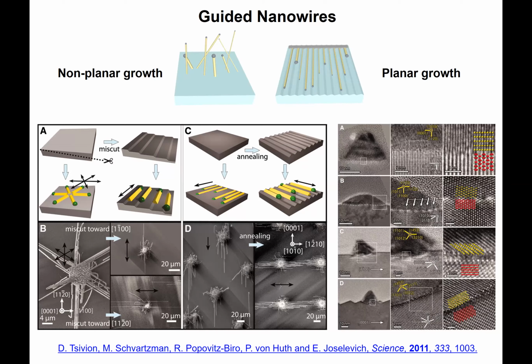And we succeeded in doing this by finding that when you grow nanotubes and nanowires on certain crystalline surfaces, instead of growing up in this disordered way, they can grow in a planar way, crawling on the surface and being guided by surface features. So this is what we call guided growth.